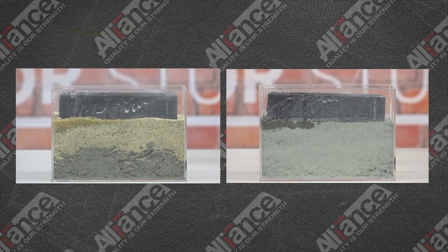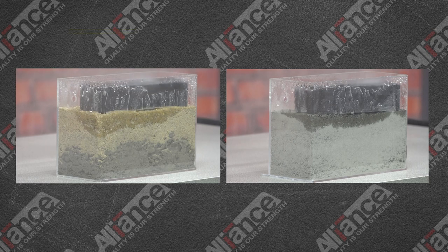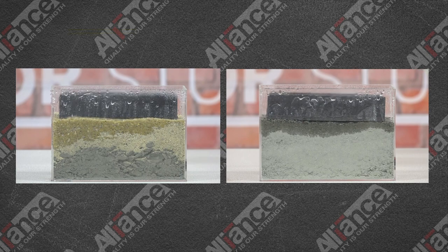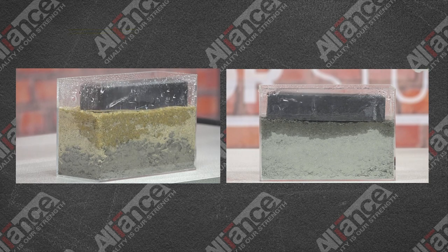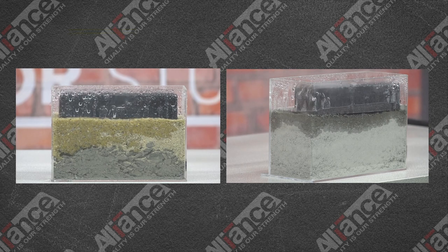You need a drainage base to install Nitro — something that allows water to freely flow through it. Concrete sand, clean chip, ASTM No. 9 stone, or No. 8 stone would be ideal. Stone dust is certainly not ideal. For a concrete overlay that drains very slowly, use polymeric sand. Stone dust is a little outdated and traps and holds moisture.